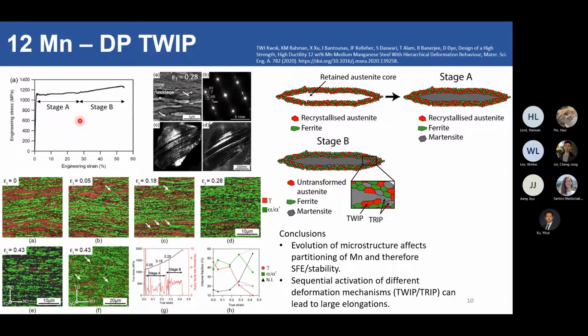So in stage A, what happens is that your core austenite grains, because they are larger and less enriched in manganese, are less stable to transformation. So the core austenite grains actually transform first. They start to transform and form martensite. Martensite indexes as ferrite in the EBSD, so we can only say this qualitatively. We cannot quantify it. So the core austenite grains begin to transform into martensite first.